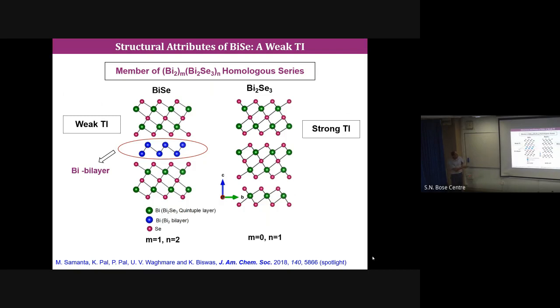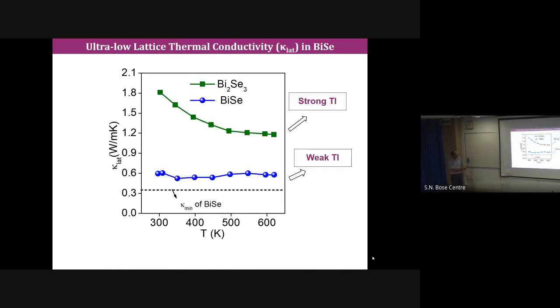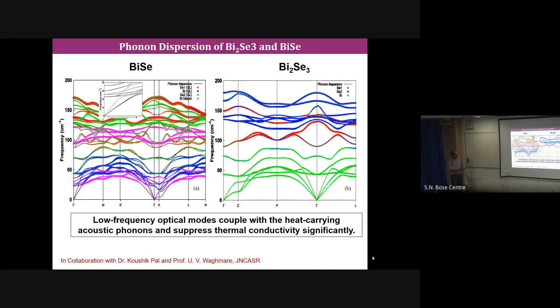As I told you, it has a Bismuth bilayer and Bismuth selenide in between, sandwiched between two Bismuth selenide layers. And this is a simple Bismuth selenide compound. So let's see what the thermal property of this is. When we measure the thermal transport, this BiSe is ultra low, which is a weak TI, and the strong TI shows high. Right?